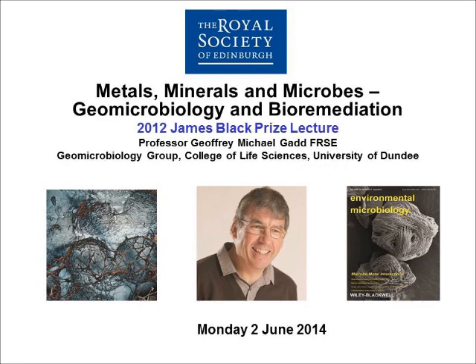So we developed one thing called the biomatrix by means of a Scottish Enterprise grant, where if you've got the concrete with the radionuclides on the outer surfaces, a biomatrix can contain the geoactive organisms, which you could feed accordingly with nutrients and oxygenate. The geoactive organisms will then put their excreted metabolites, the organic acids, protons, etc., into the concrete, dissolving the radionuclides, which will then diffuse and be taken up into the biomatrix, eventually resulting in loading of the biomatrix, where they could become biomineralized, as various minerals precipitate out of solution. And then you could remove the biomatrix for recovery or containment in a small volume, or disposal by other means.